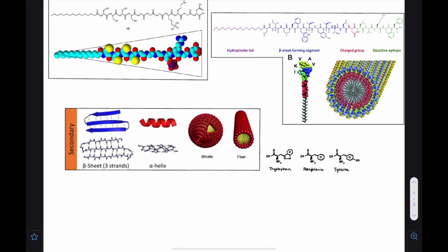Supramolecular assembly of peptide amphiphiles relies on protein assembly pathways because these pathways are critical to correct folding and function of proteins. The main way that this is done in these amphiphiles is by hydrogen bonding. The primary sequence of amino acids present in each molecule utilizes hydrogen bonding to fold into secondary peptide structures, which include alpha helices and beta sheets.